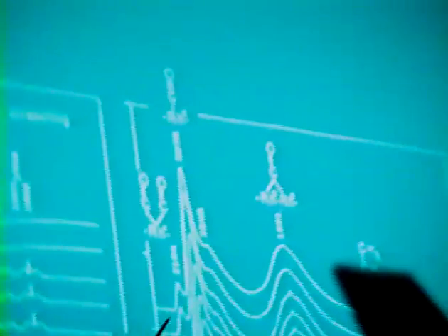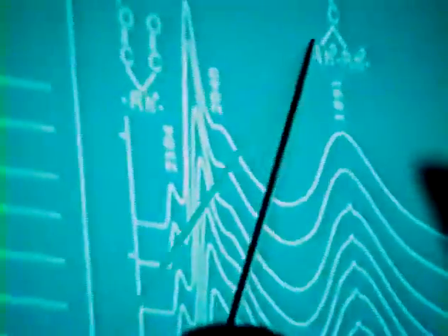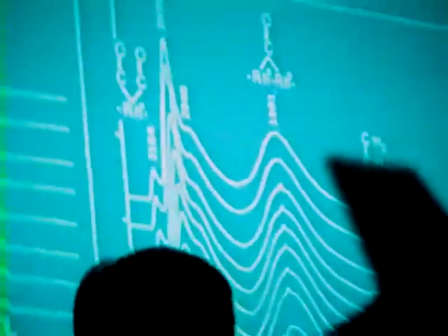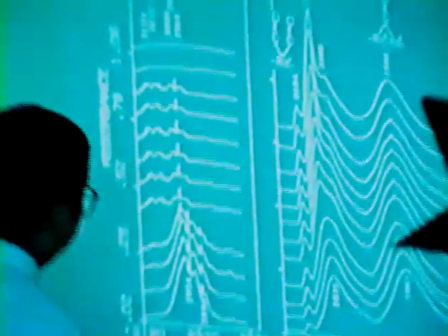Okay, this is a result of a reaction of ethylene and hydrogen with the adsorbed CO on the reduced rhodium catalyst. Let's take a look at this infrared spectrum here. Adsorption of CO on the reduced rhodium produced a linear CO band, a bridge CO band, and a gem-dicarbonyl band. And this is reduced rhodium on silica. The crystallite size of this catalyst is around 92 angstrom, determined by X-ray diffraction.